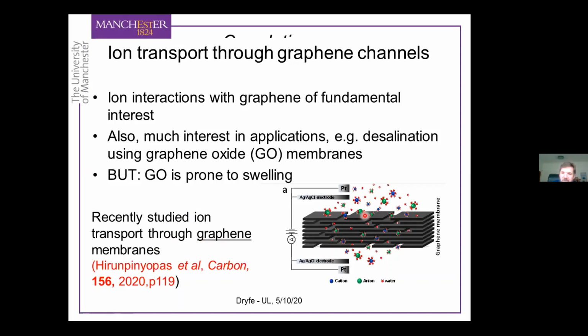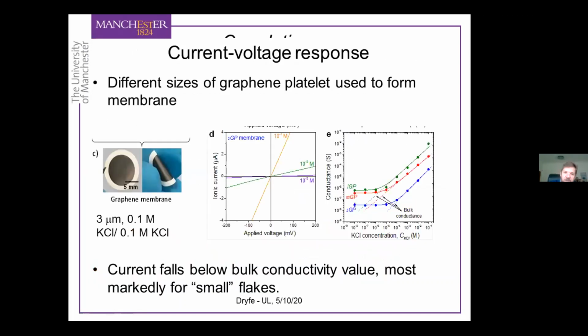And then you can do the simple experiment where you look at potential induced transfer. If you have two electrolyte solutions on either side of your graphene membrane, you can look at the current voltage response of that graphene membrane. And so here's a picture of the graphene membrane, which we've made by filtering it onto a polymer support, and this is entirely flexible because it consists of lots of graphene flakes. The membranes themselves are several microns thick, but obviously they correspond to thousands of layers of individual graphene platelets, which are restacked. And you can look at the current voltage response of these graphene membranes.